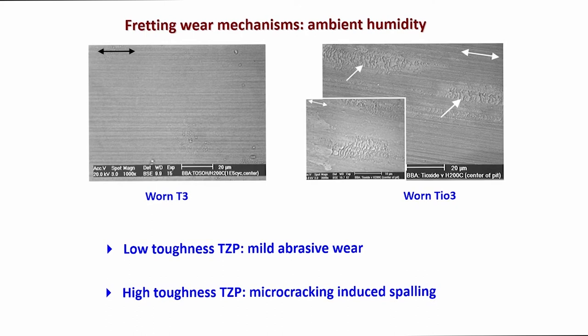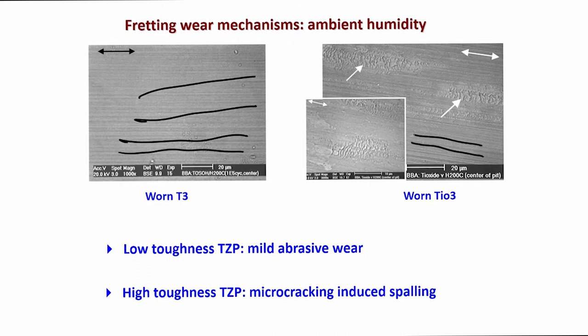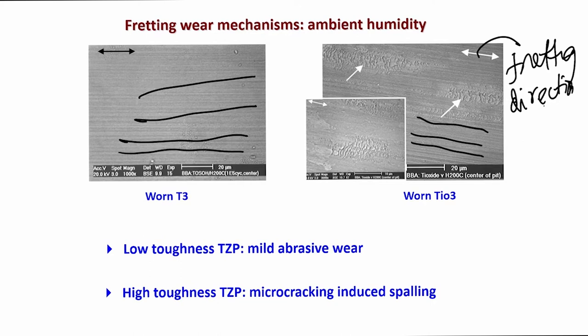Now, if you look at the SEM images of the worn surfaces, as I have been repeatedly telling in these NPTEL lectures, in this particular lecture we always emphasize discussing and describing the wear mechanisms based on various microscopic observations. And so is the case in this present case study. What you see is that there are very clear abrasive scratches in that 3 mole% tetragonal zirconia, aligned towards the sliding direction or fretting direction here. This is your fretting direction. But you will see some additional observations.